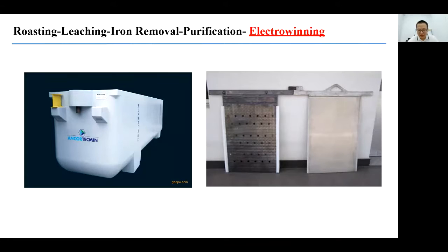And for the anode, here we are using the lead and silver. Same reason for this. The lead and silver are stable in this system. We are producing oxygen in the anode reactions, and we are using the anodes in acidic conditions, so they should be stable in acidic and sulfate system, and lead should be the first option.